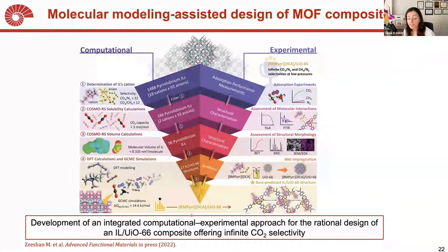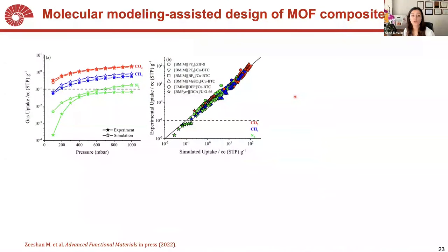And after we found this composite from the computational study combining DFT and GCMC, we went to do the experimental part, and with wet impregnation, we inserted this ionic liquid into the MOF. And after characterizing it, we measured the CO2, methane, and nitrogen adsorption isotherms.